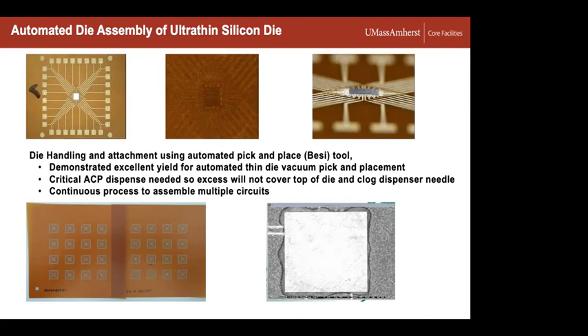So after they're diced, you're able to eject them, pick them up with a vacuum, and then position them and assemble them with a conductive, one-dimensional conductive adhesive, so that you can get good alignment and good conductivity of all electrodes on the lead. So in the bottom right, we show an example of one where we have placed that onto a test circuit. And I think the upper left, so we first have one on this test array that we've used. And again, these are, I think, line width of about 60 microns, spacing of about 30 microns, where the critical pads are on the silicon.